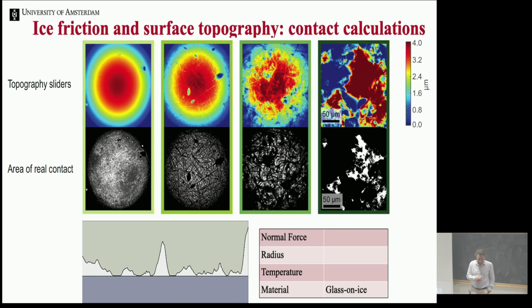And then I can do a finite element calculation, which is the standard thing that people do in friction mechanics. I put in the measured surface roughness. I assume that my counter surface is flat, and then from the roughness map I can get the real contact area between the two surfaces for a given normal force. And if I have the real contact area for a given normal force, I can calculate the pressure and then compare it to the penetration hardness.